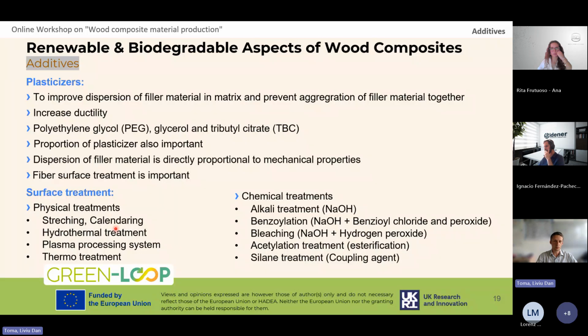For combining the wood composites and the wood fibers, a third part comes into place, which are the additives or fillers. This can be plasticizers, which is an additive to improve the dispersion of filler material in the matrix and prevent aggregation of filler material together. This also has an influence on the ductility of the material. Some of the plasticizers usually used, which are shown in the literature, are polyethylene glycol, glycerol, or tributyl citrate.